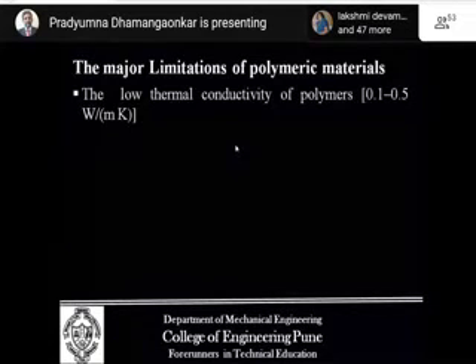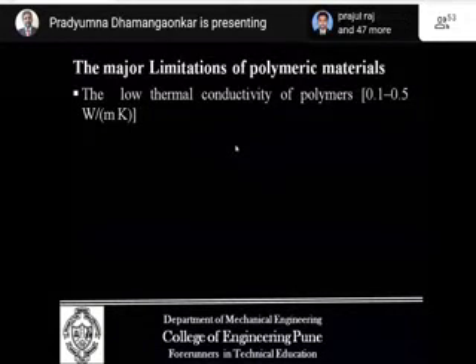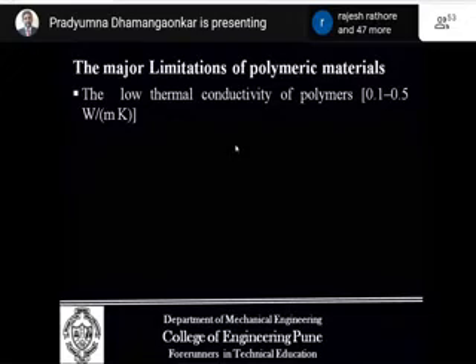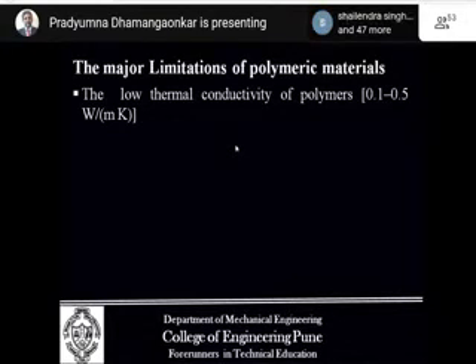These limitations are the low thermal conductivity of polymer. It is hardly 0.1 to 0.5 watt per meter Kelvin. Just think of what is the thermal conductivity of most of the conductive material, steel or stainless steel, iron or any copper.